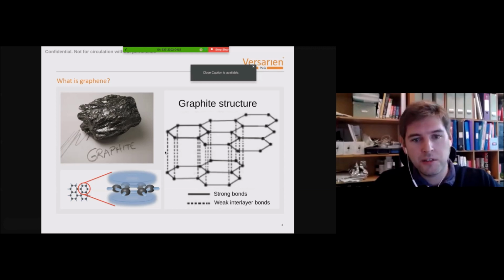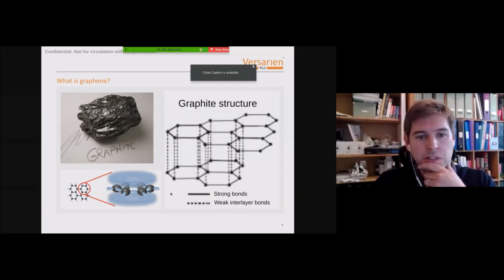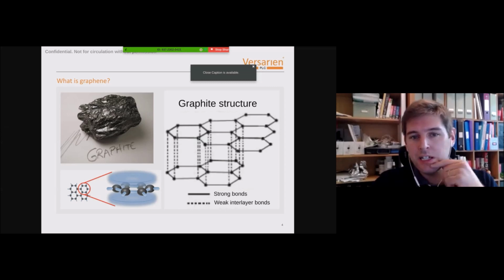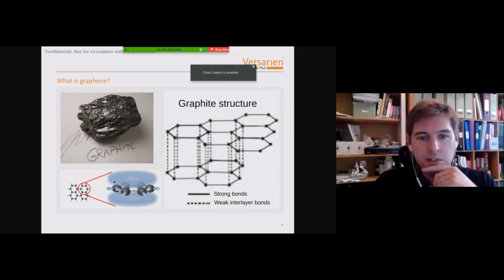And the property that causes that is electrons, so how we conduct electricity. Normally when chemicals bond to each other, for carbon, you have to have 4 bonds, but in graphene and graphite, each carbon atom is only bonded to 3 others. So that gives a unique property that there's 1 electron or one bond missing. And actually all these electrons are sitting between the layers. And that means these electrons are freely able to move around the structure. And that gives rise to electrical conductivity across the structure.